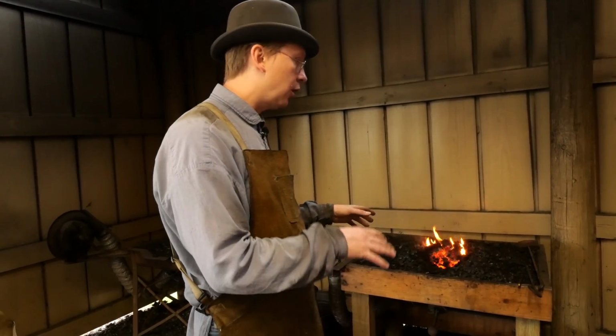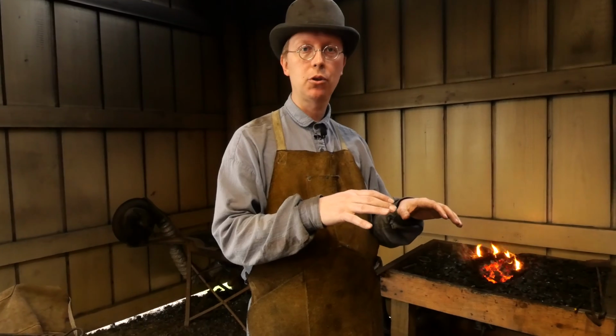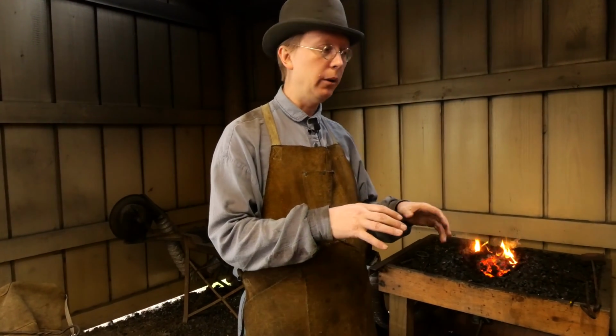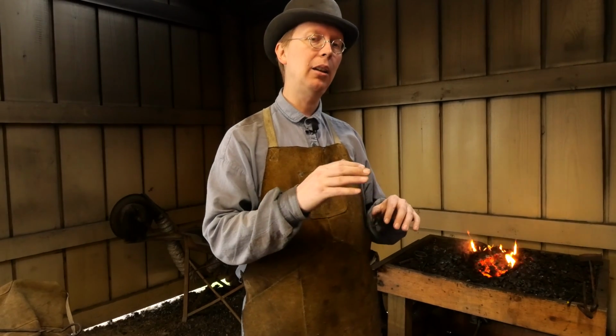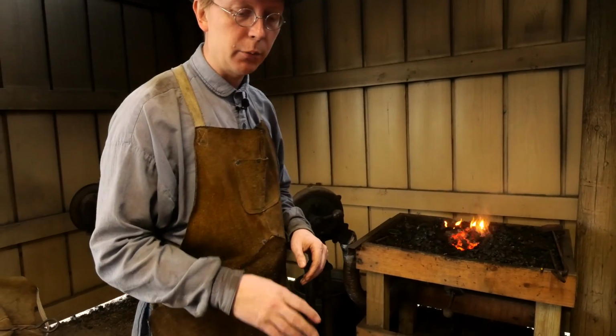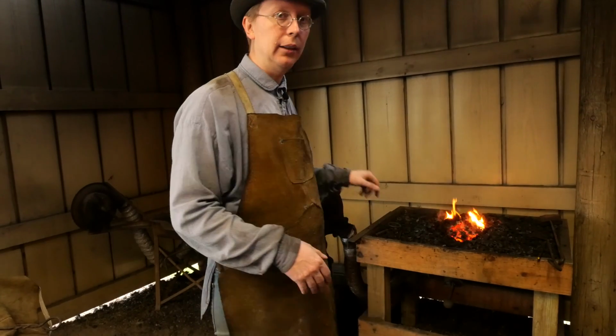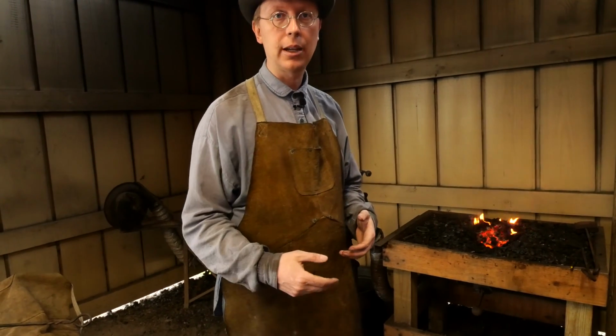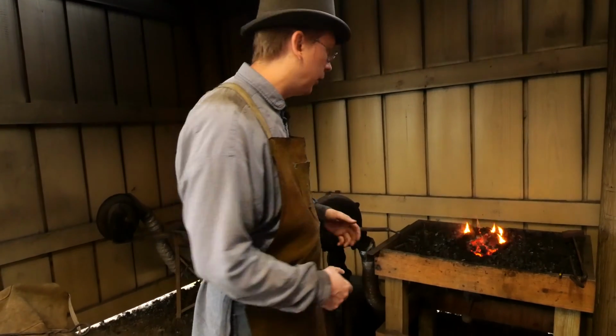Mild steel starts getting ready to weld just before the temperature that scale melts at. And so if I've got a pretty reasonable piece and I don't mind getting it a little hotter than I technically need to for welding, then I won't bother fluxing it. I'll just go straight in and weld it up and try and take it up a little bit hotter so that that scale gets to liquid and can get pushed out of my weld. And I get a nice weld without having to flux. When I'm doing chain links, a lot of times I'm doing a lot of chain links and I try and make it as fast as possible. And the extra step of heating it up, brushing it, putting flux on it, I just find is not worth the extra time for any difference in quality, which I don't really notice on these chain links.